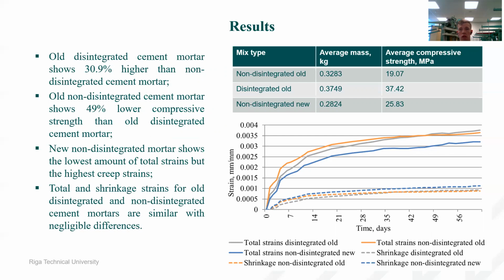If we look into complete strains from the creep test, we can see that old cement mortars, the disintegrated and non-disintegrated ones, show similar values, and the creep for the non-disintegrated new cement mortar is about 10 to 15% less. As for the shrinkage strains, we can see that for the non-disintegrated new cement mortar, the shrinkage is a bit higher than for the non-disintegrated old and disintegrated old cement mortars. This is mainly because of the higher hydration temperature and the moisture evaporation due to the higher hydration temperatures for the new cement mortar.